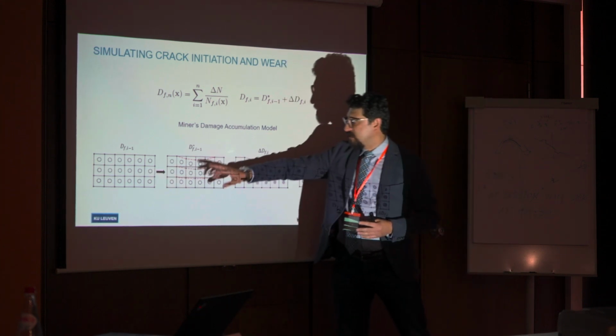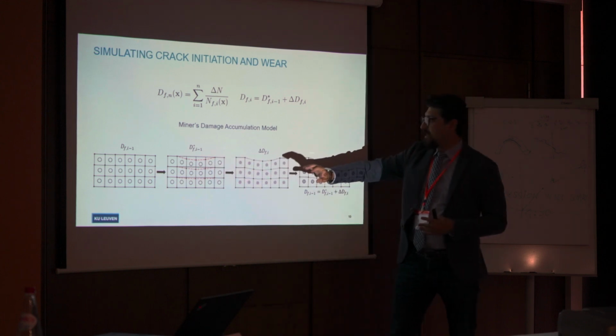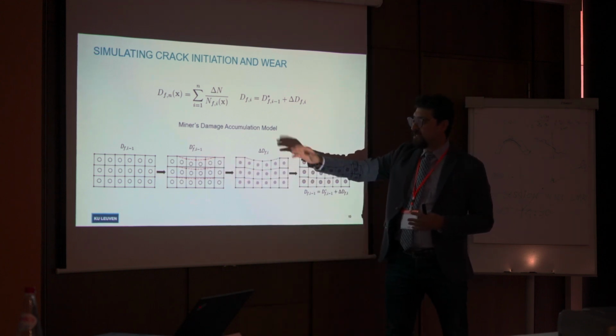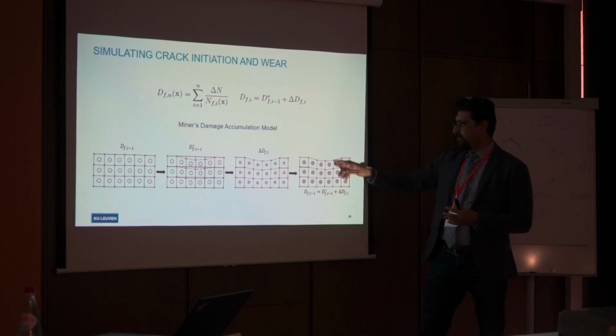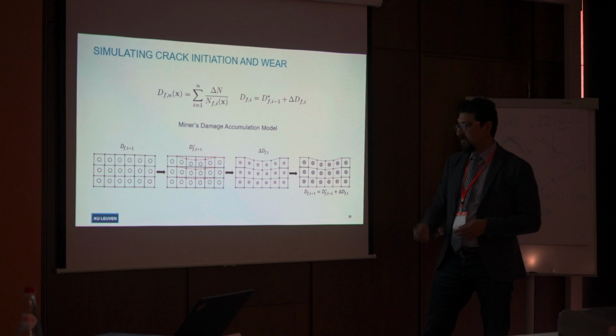So then we run the test, we calculate the stresses, and then when the damage is accumulated, it's combined with the new wear profile, and we continue that till one of these elements fails because of the crack initiation.